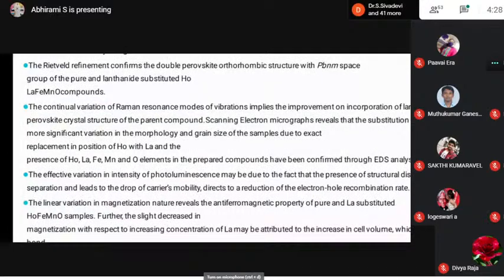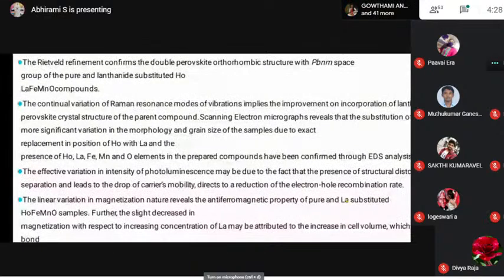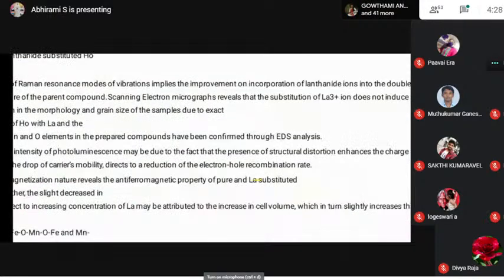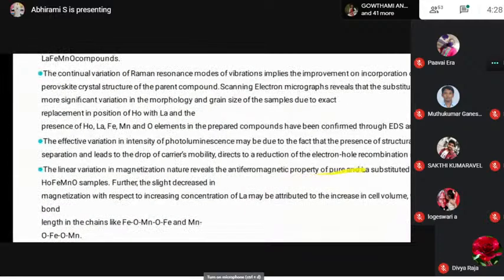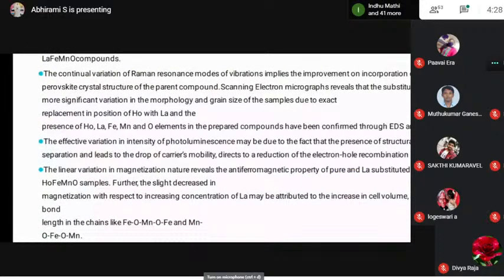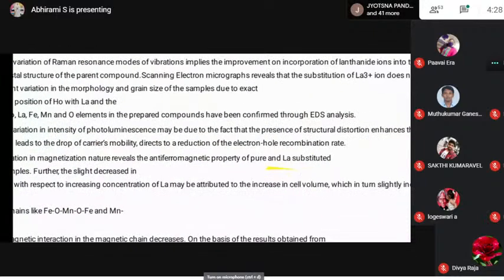The effective variation in the intensity of the photoluminescence may be due to the presence of structural distortion, which enhances the charge separation and leads to the drop of carrier mobility. This then directs the reduction of the electron-hole recombination rate.